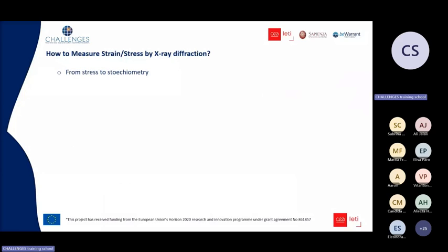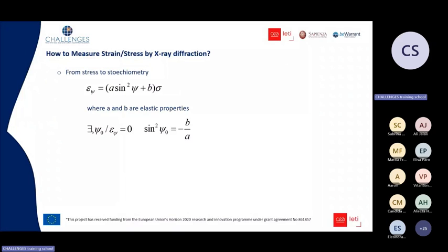I would like to finish my part here saying two words about the fact that from this equation, we can also extract the stoichiometry of the material. Why? Because, well, I said that the strain depends linearly with sine square psi of the stress, where A and B are the elastic properties of the material. You can see there exists a specific psi angle, I note this psi zero, where the strain should be equal to zero. And this specific direction only depends on the elastic properties of the material.